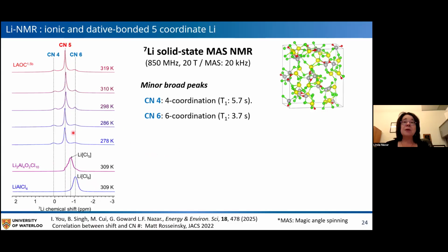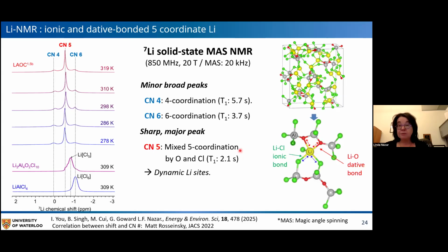And you can see that the T1 relaxation times are slower for the 4 and the 6 coordinate system, where it's much faster for this 5 coordinate center, which dominates. And we were able to see this 5 coordination by doing the AIMD simulations. This is Dr. Singh in my group, Vorrada Singh.